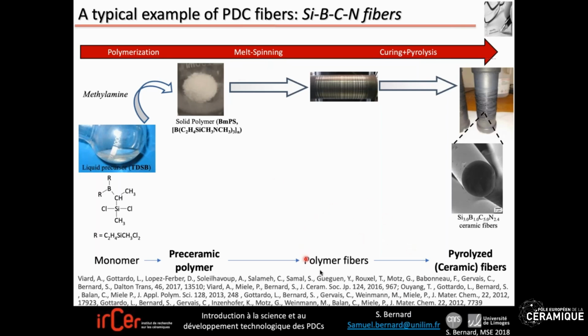So you form your polymer fiber, then your polymer fibers are cured and pyrolyzed to form your pyrolyzed fibers, I mean the ceramic fibers, in the SiBCN process. So I didn't mention this curing process, which is in general applied just to produce fibers. It is essential to render your fibers infusible in order to avoid the collapse of your fiber during the further pyrolysis and heat treatment to more than 1000 degrees C.